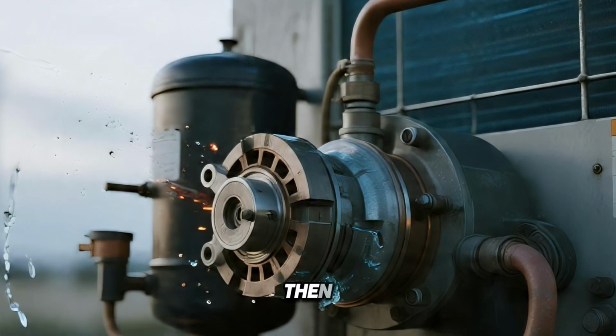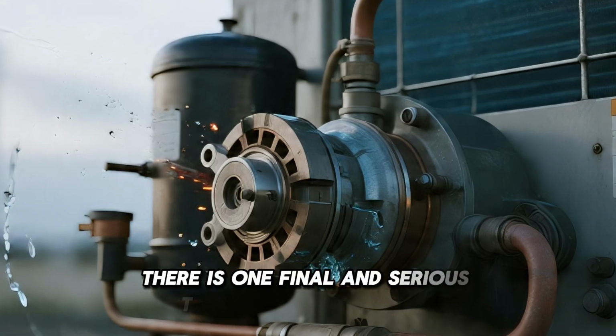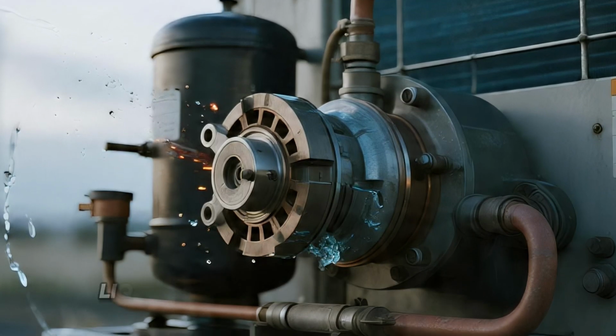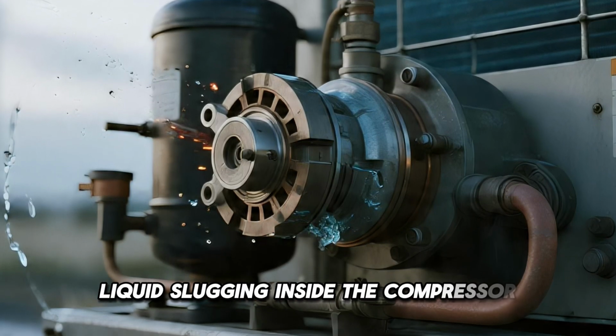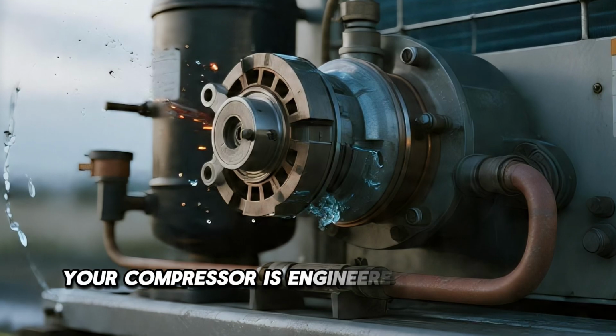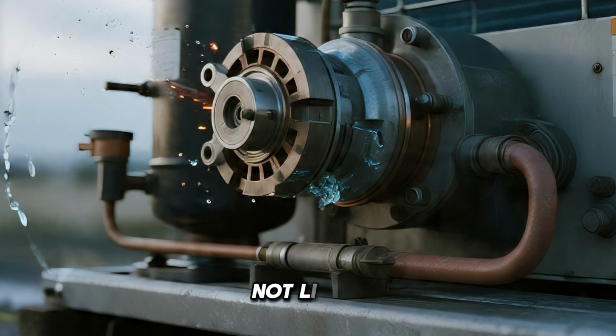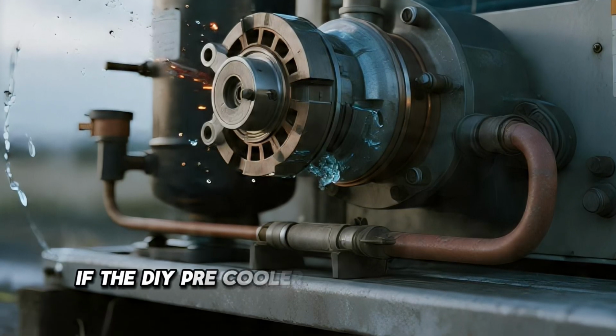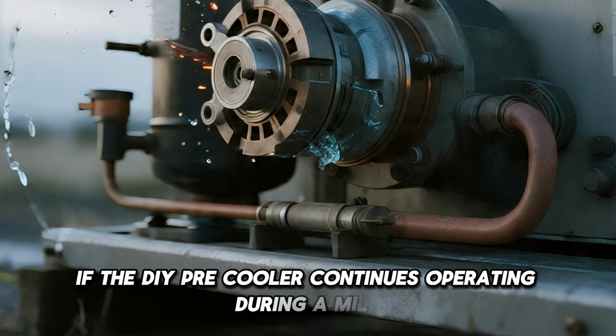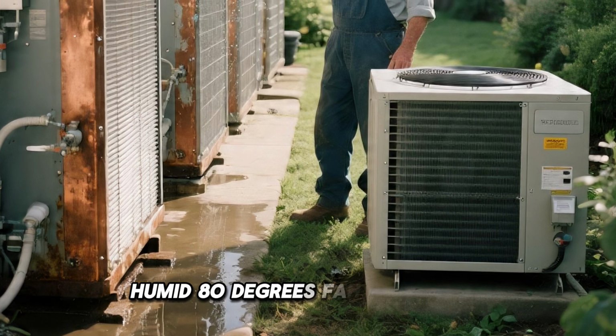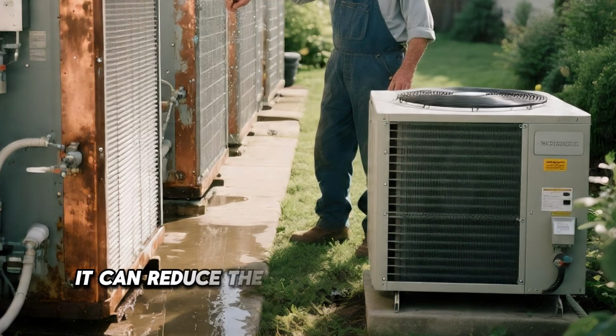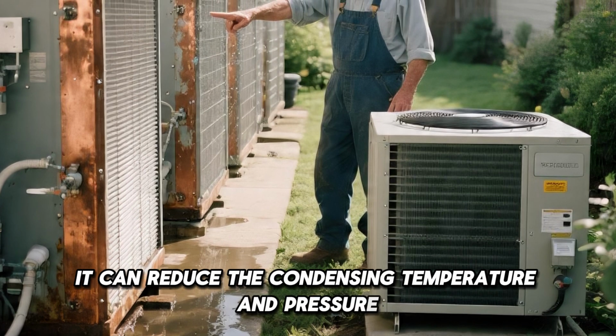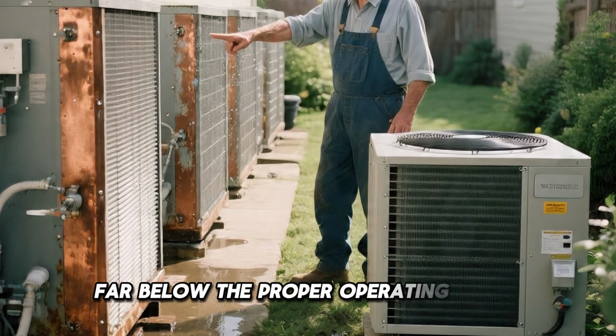Municipal water also contains chlorine, which aggressively attacks the protective oxide layer on aluminum and accelerates corrosive pitting. Then there is one final and serious thermodynamic danger: liquid slugging inside the compressor. Your compressor is engineered to compress gas, not liquid. If the DIY pre-cooler continues operating during a mild, humid 80 degrees Fahrenheit day, it can reduce the condensing temperature and pressure far below the proper operating range.